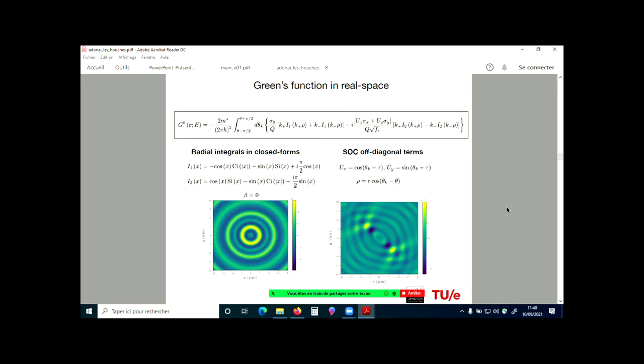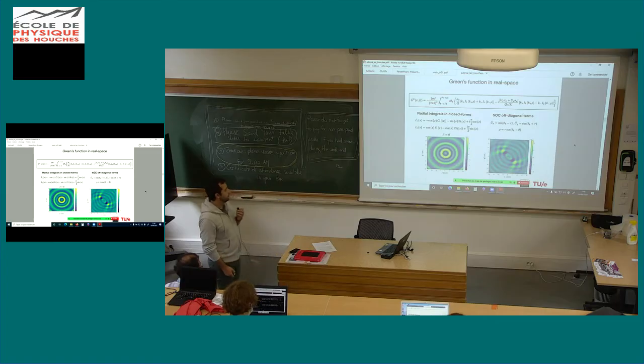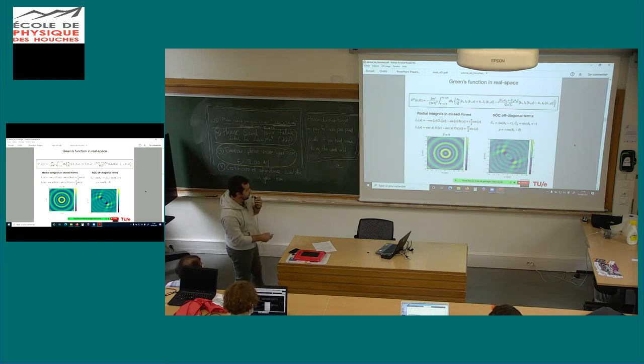But the interesting thing that I mentioned before about the band structure curvature anisotropy is reflected here in the local density of states in real space. So the first case is just for the Rashba case. That's nicely isotropic. And when you have both, you can see the interference between them.